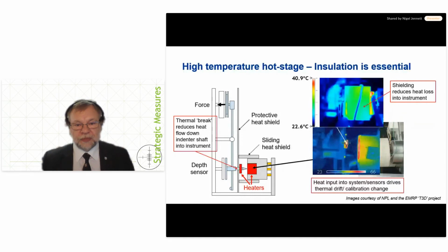Take-home messages: thermal drift and calibration of your indentation system are all driven by the same things that they were at room temperature. In other words, a change of temperature of the environment will cause changes to those things. So you still have to control that. And you should not, in your mind, link necessarily what's happening inside the hot zone to the creation of thermal drift, even though that is a hot thing. It's the leak of heat from the hot zone, generally speaking, which causes you the problems.